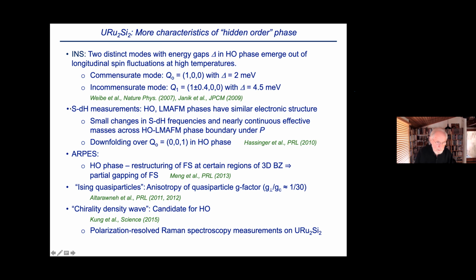Okay, and then from Shubnikov-de Haas measurements, one finds that the hidden order and large moment antiferromagnetic phases have similar electronic structures. So there are only small changes in the SdH frequencies and a nearly continuous effective mass as you go through the hidden order, large moment antiferromagnetic phase boundary under pressure. And this suggests that you are doubling the lattice constant along the c-axis, or downfolding in Q space, in the hidden order phase. So that's one feature that is suggested by these measurements.